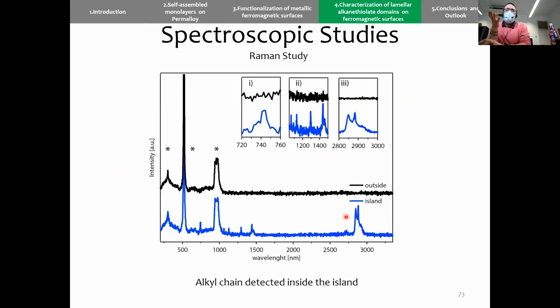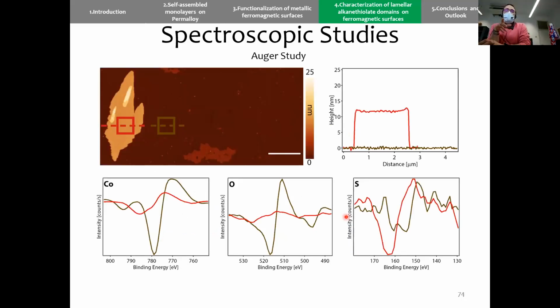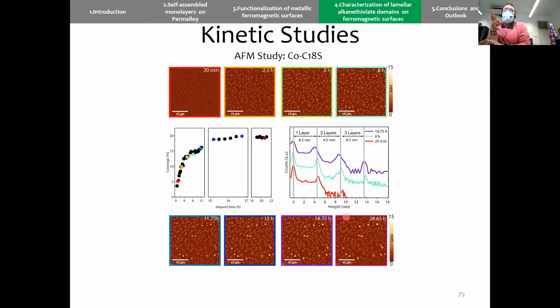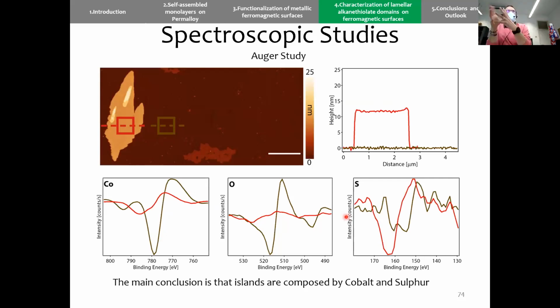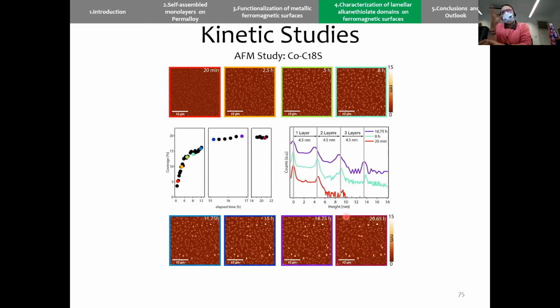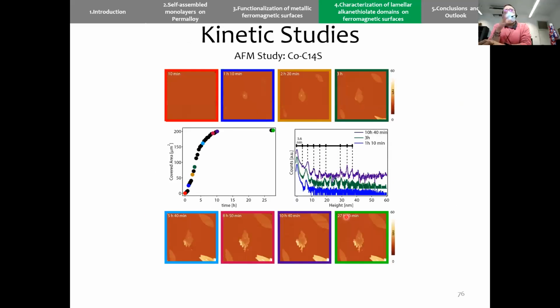Thanks to Raman, we have observed the presence of the alkyl chain only inside these lamellar structures. By Auger, we determine the presence of cobalt and sulfur, and so in this case, we could characterize this kind of structures. We also observe that they can grow over time, but to me, the most impacting is this one. Not only by AFM, we also observe it by eye, that over the course of 16 hours, plenty of this structure appears.